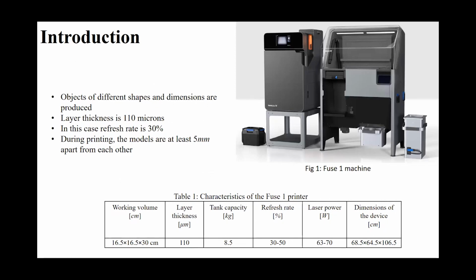The 3D printer used in this research is Fuse 1, and it is shown in this slide along with its features. With this technology, objects of different shapes and dimensions can be produced at the same time. The only condition that must be met is that the models are at least 5 millimeters apart from each other. The thickness of the powder layer is 110 microns, and during the sintering process, one row of powder is sintered at the same time.